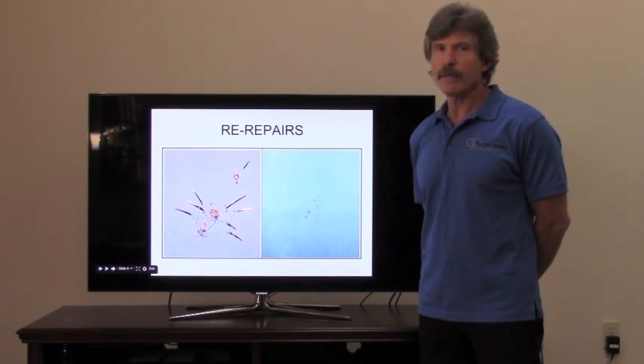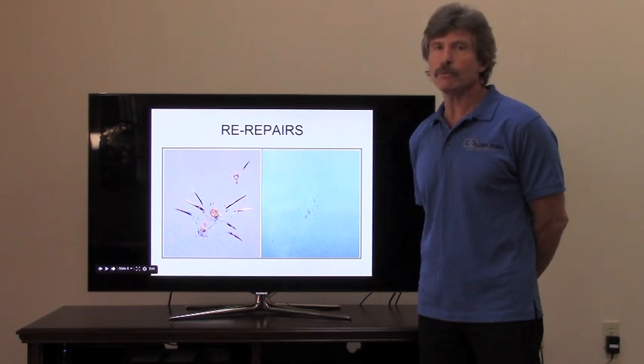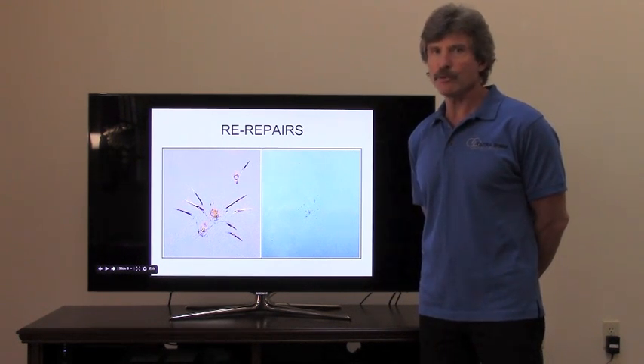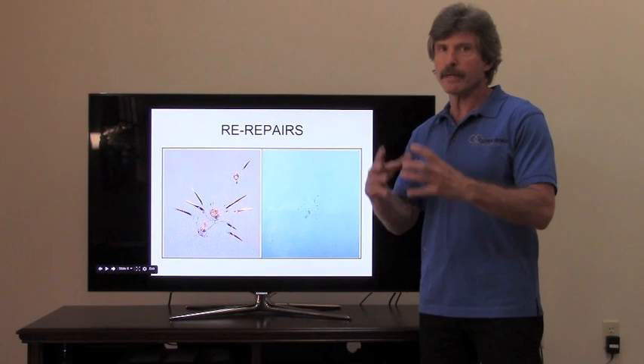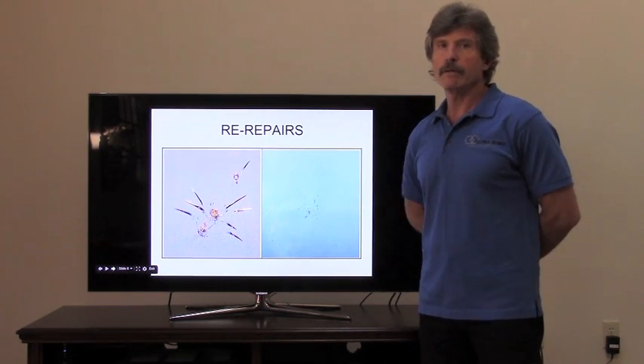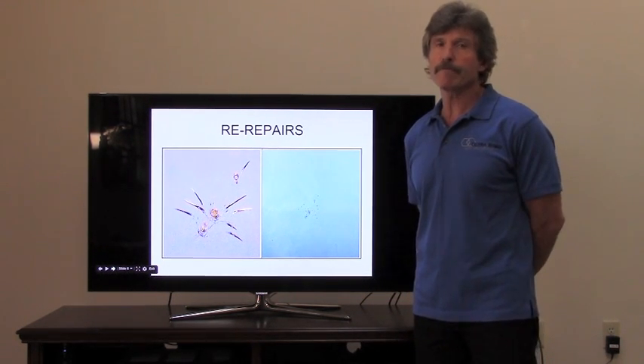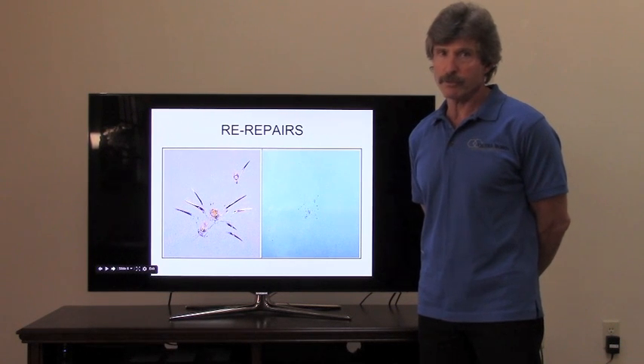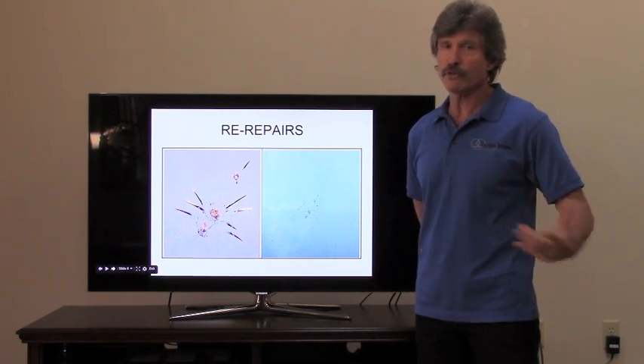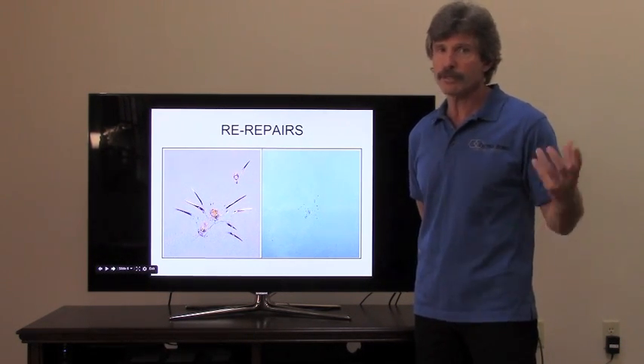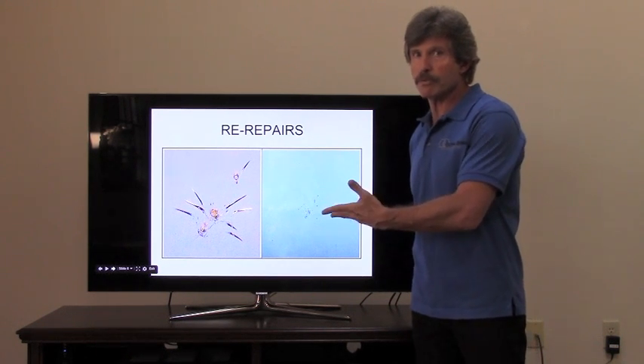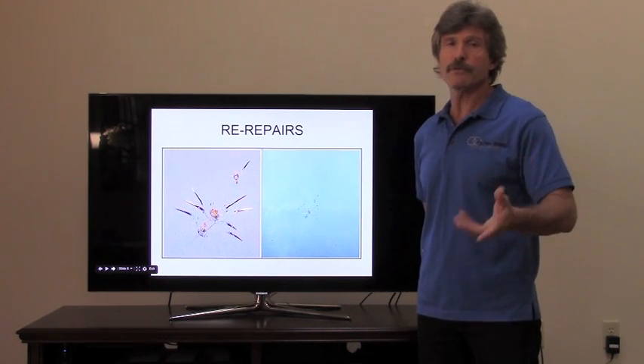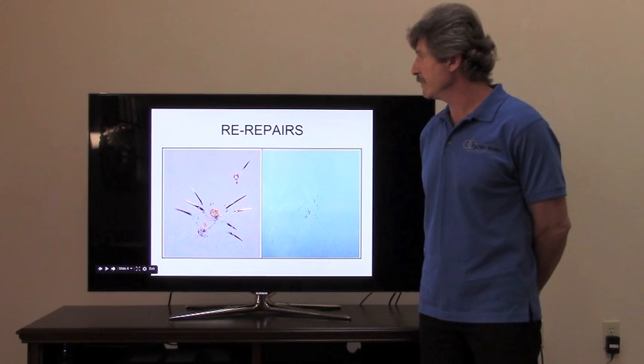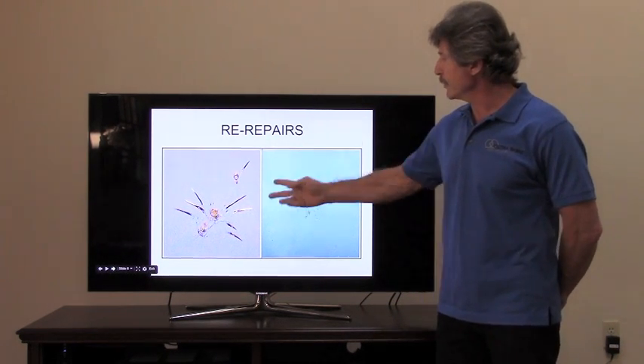And the one reason that occurs is, #1, their tool pulls up on the glass. When you pull up on the glass, you shrink the break and close the cracks. And so less resin gets in there. They also don't cure it under pressure. So they have less resin than you normally get in there. Then they don't cure it under pressure, which creates those problems I was just talking about of shrinkage and no bond to the PVB.